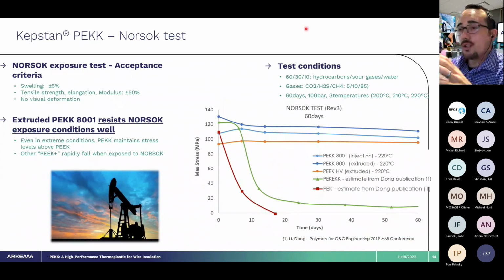In that same realm of environmental resistance, chemical resistance, we have done NORSOK testing. NORSOK testing is very common in oil and gas for downhole conditions. The acceptance criteria for the NORSOK exposure test is a limit of plus or minus 5% on swelling. The tensile strength, elongation, and modulus cannot change by more than 50%, and there can be no visual deformation. That's the characteristic of the polymer going through the test.